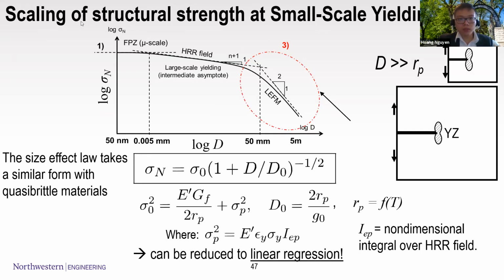So the assumption that I just mentioned applies for small-scale yielding, when you have a structure that has a size bigger than the yielding zone size. And that ends up with a similar formulation for the scaling or the size effect formulation. However, the relevant terms are different from the quasibrittle materials, and some of the details should be read in using the non-dimensional integral over the HRR field, which takes into account the shape of the field.